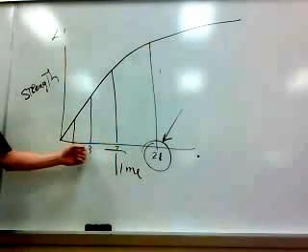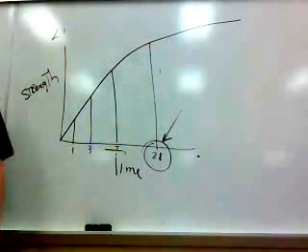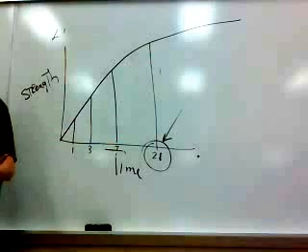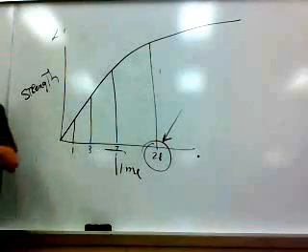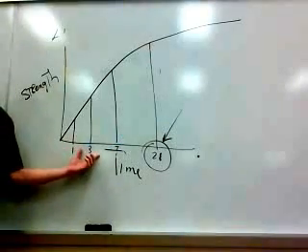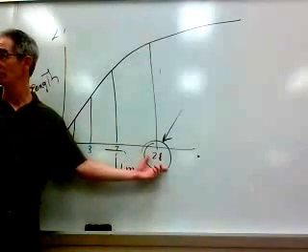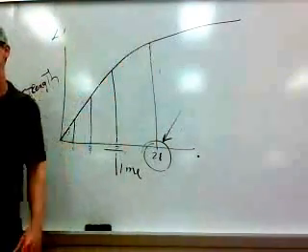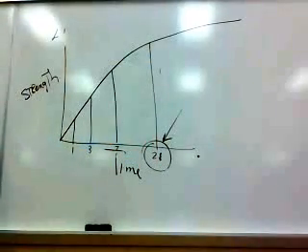But we do know in normal concrete that there are relationships. There's a relationship between 7 and 28 days, or between 3 and 28 days. Now, are those perfect relationships? No. But are they general relationships? Yeah. If you had no admixtures in a concrete, most people could look at a 3-day strength and say, that's probably roughly about 50% of what you're going to get at 28 days. So it increases much more quickly in the first 3 days than in the next 25 days. At 7 days, most people would say probably around 70%, 75%.